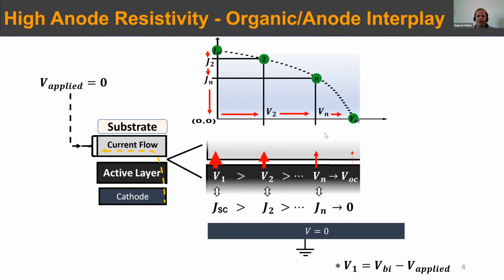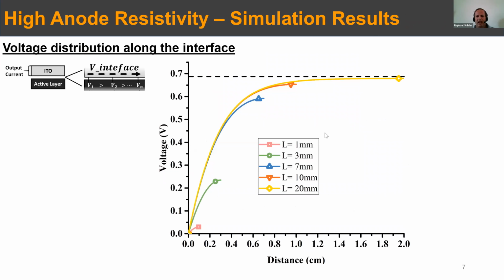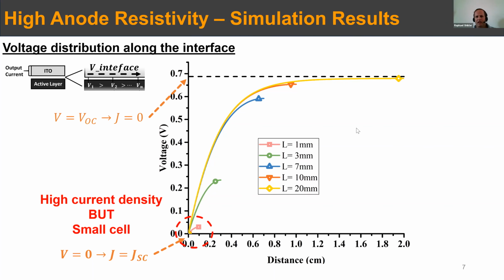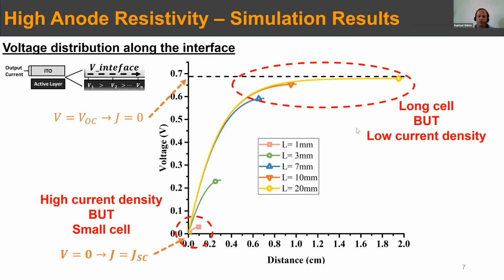charge collection. If you look at how the voltage is developed, you can see that in a P3HT:PCBM system, when you are at a very short side, about 1 millimeter, most of the current is the same, and you get the same short circuit current all over. When you increase the device size a bit, obviously there is a larger and larger development of voltage. And when you get to devices which are longer than 1 centimeter, you can see that the voltage development across the device is saturated. And obviously, at this section, we have a long cell that doesn't really contribute to the current.